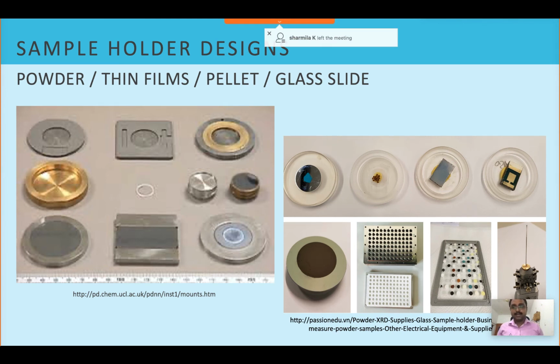Next, coming to the sample holder, you can see there is a variety of sample holders. Why? Because we have a variety of samples. So according to the sample, we should be able to select and place the sample holders. For example, if you have 5 grams of powder, you can take a very large container where you can fill all the sample, because it is not destroying the sample. So XRD is one of the non-destructive techniques. So the sample will not be destroyed. In that way we can place the entire sample for X-ray diffraction.